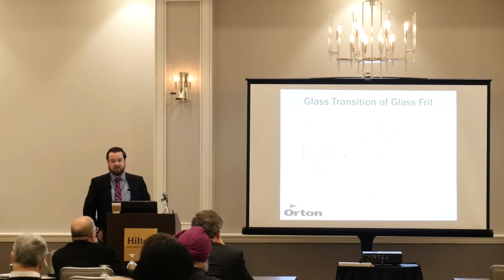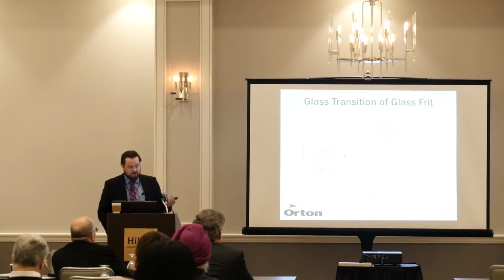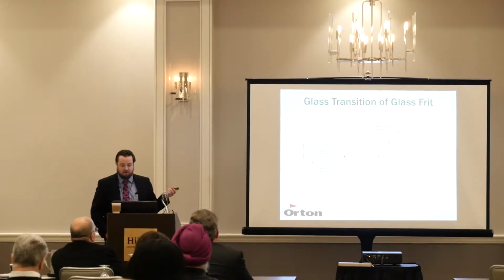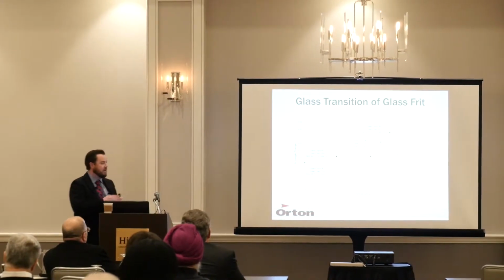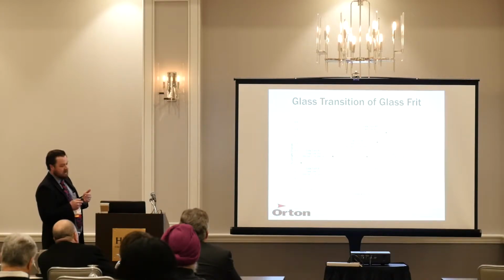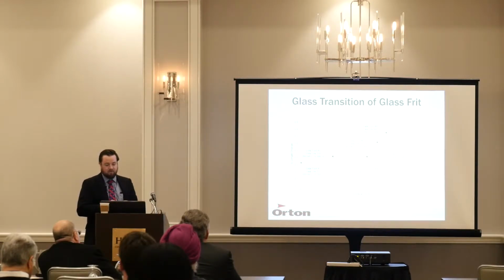A much more powerful and direct correlation here for you guys, I imagine, is the glass transition. This really starts to help out with the material processing temperatures and where you're going to work with your glass and where it's going to be applied. So here it shows you very straightforward how to calculate the glass transition from a dilatometer run using two linear sections of the material. You can see that it's at the convex of the curve where it starts to change and really start to act like a liquid. There it's labeled at 410.54. So it's a very powerful measurement, an added value of running glass in the dilatometer.